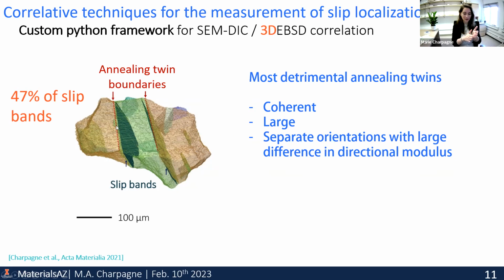From the nature of the plane, it's actually the same crystallographic nature. So these two are actually fully parallel, but for some reason that we don't understand just yet, the slip bands actually form close to the actual twin plane, but not on it. But close, when you say close, to me, if you say 100 nanometers or 50 nanometers, that's like miles away from an atomic point of view. So it would mean there had to be some strain propagation over quite an extended distance, I guess, which I guess is how you're maybe imagining it?